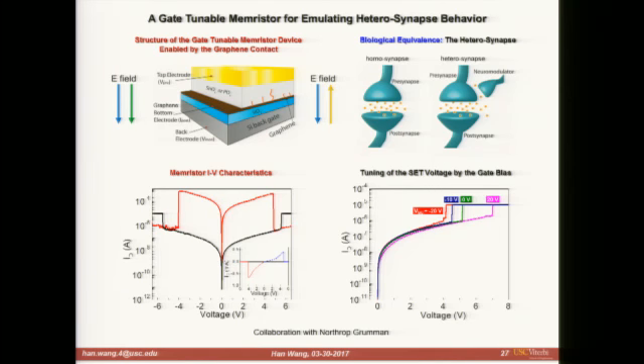In our work, we made a bit of modification to the traditional memristor devices using 2D materials. Instead of using two metal contacts to make the device, we replace one of the contacts, in this case the bottom one, with a piece of graphene. Graphene is a semi-metal, so you can use it as a contact and inject carriers into this median layer.